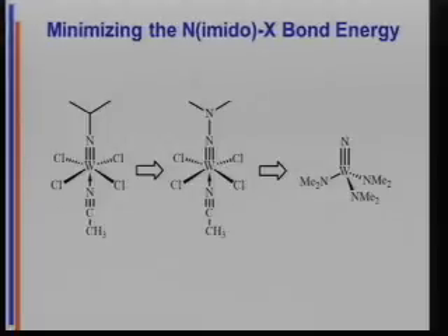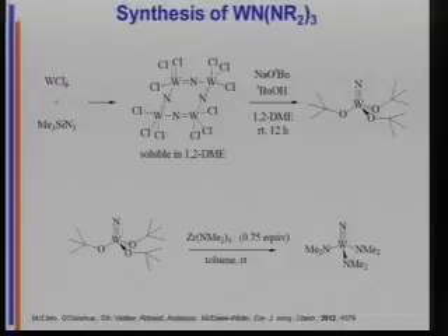Okay, so that molecule looked really interesting. My students figured out how to make it in 3 steps from commercially available material. Okay. So we start from tungsten hexachloride and TMS azide, and that gives this tetramer of the terminal nitride with 3 chlorides. And this chemistry had been done by the Dehnicke group in Germany a long time ago.